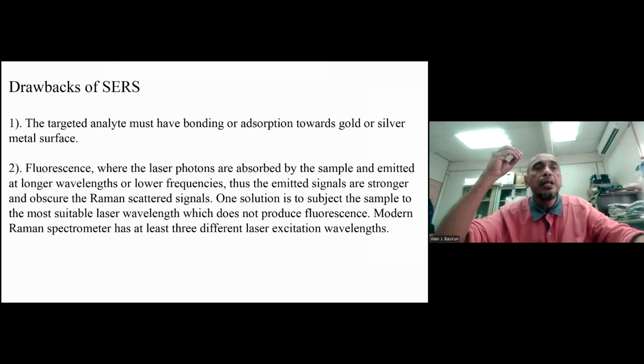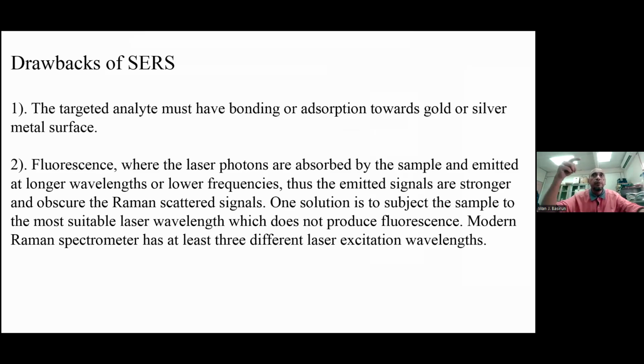So that's why in a typical Raman spectrometer, you have at least 3 different laser excitation wavelengths: high frequency, low frequency, and mid frequency. So you can choose which of these is suitable for the compound, and suitable meaning it must be able to differentiate between fluorescence and the normal Raman scattered signal. Usually for dealing with organic compounds, you run the fluorescence spectrum and make sure that the Raman laser excitation is not in the same frequency region as the fluorescence spectrum of that same compound. So that is a simple experiment setup to solve the fluorescence problem.